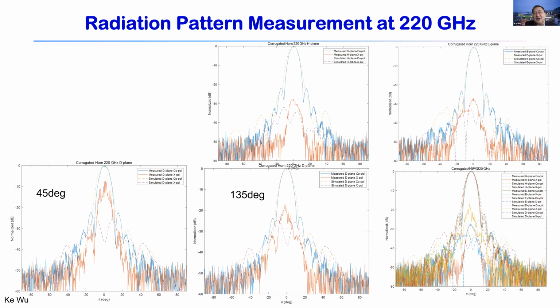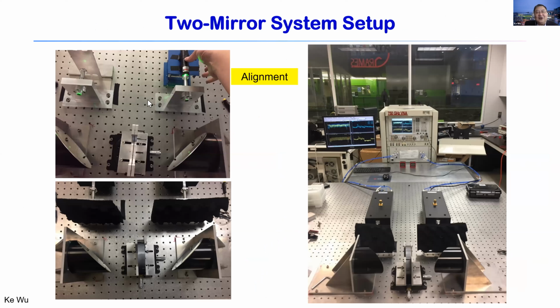So this is 220 gigahertz. Again, this is 45 degrees, 135 degrees. The co-pole and cross-pole measurements are still very satisfactory, even though there is some beam deviation and some beam distortion, with a slight enlargement of the beam here, but still satisfactory for our measurements. So we use those corrugated horn antennas.